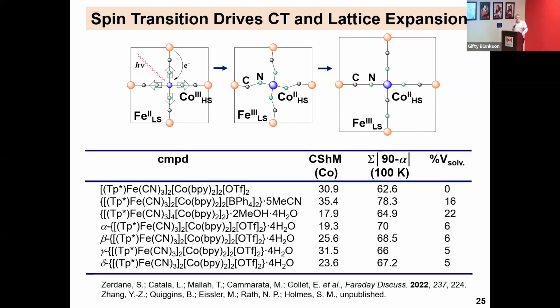And to further illustrate that I think we have a good handle, at least from a molecular standpoint, I failed to mention that this was done on Prussian blue analog. For our molecular compounds, I think we have an analogous argument in the absence of their data, in that if you look at most of these, they have a unit cell volume, and more importantly, a volume of solvent around the molecules that's small, less than about 10. The ones that are 16 and 22 have much different structures and nuclearity. So they're the statistical outliers.